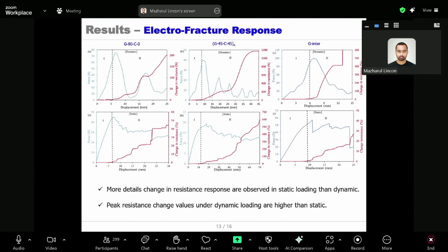During crack propagation, the change in conductive network happens faster in dynamic condition. On the other hand, in the static case this crack propagation happens very slowly, which provides an alternative path for the current to flow. That's why change in resistance happens very slowly and the peak resistance change is smaller than the dynamic case.